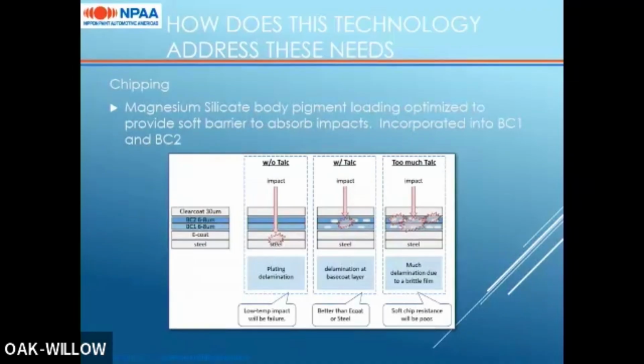So just as an example, if you have a system without any talc, I'm sure all of us who design paint coatings know the risks, but it will allow impacts to occur that cause damage all the way down through the coating layers. With the talc level optimized, it creates a good coating that prevents delamination below the base coat. So while there may still be coating loss, the coating loss will typically be within the top coat layer itself, so there's still adhesion to the substrate, which protects the underlying surfaces. If there's too much talc in your coating, then it causes delamination as well, as it breaks and interrupts the resin too much.